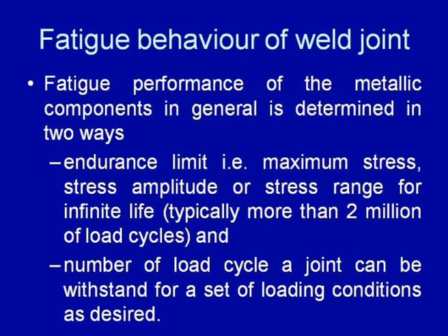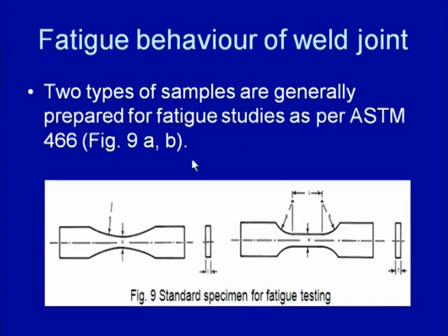for given loading conditions. So, if you have identified the kind of fluctuation which will occur in the loading magnitude, or the stress range or the stress amplitude is available, then for that particular stress amplitude, how many load cycles the component can withstand. So, the fatigue life for given loading conditions or the endurance limit, these are the two things which are identified when the fatigue behavior of the weld joint is studied, and this is done using two types of samples.